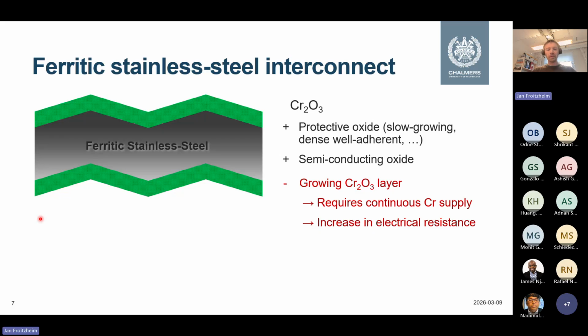And it requires a continuous chromium supply. So if we don't continue to supply chromium here at the metal oxide interface, the chromia scale, we'll start to form iron oxides, which grow much, much faster. So that we need to avoid.